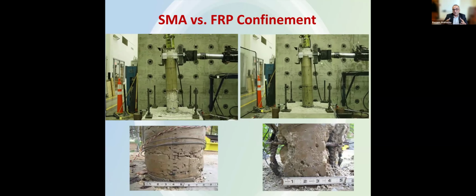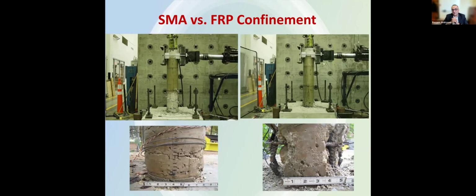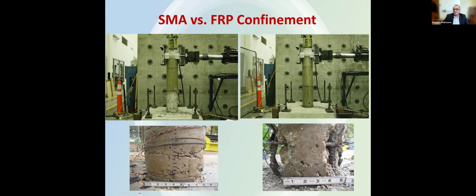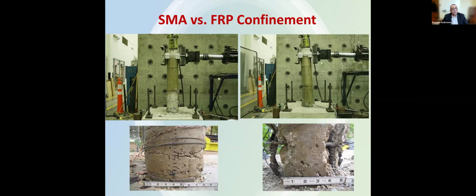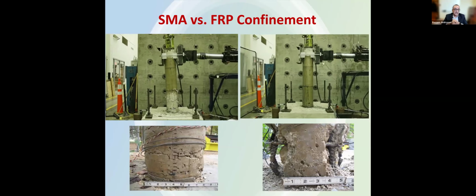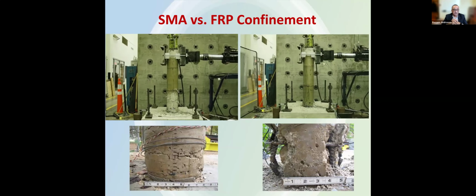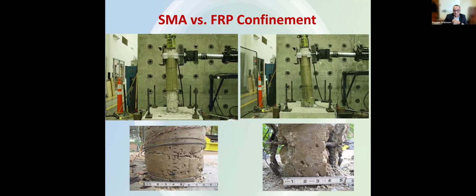Not only that, when we uncovered the columns and took all the wraps off and inspected the concrete underneath, for the case of the FRP column, almost half of the cross section was completely gone. It's unusable. While the one on the left, yes, there are damages, but it's in a much better shape, which will affect the post-earthquake functionality and the repairs, the downtime, and all this important stuff that decision makers and bridge owners have to make after an event like an earthquake, for example.